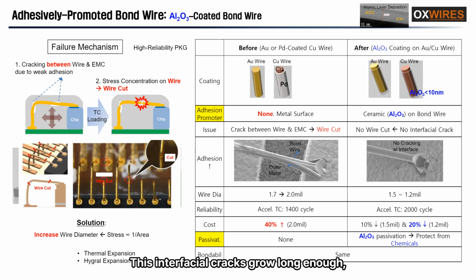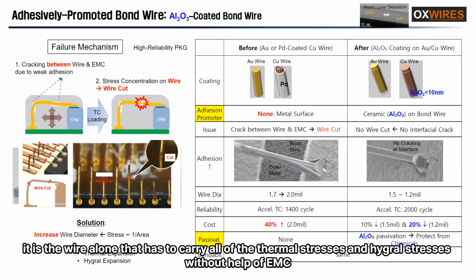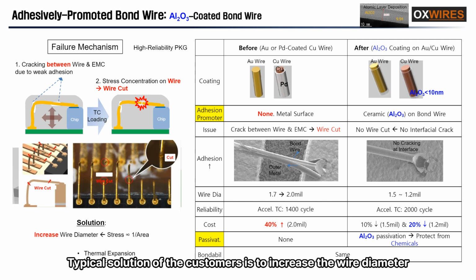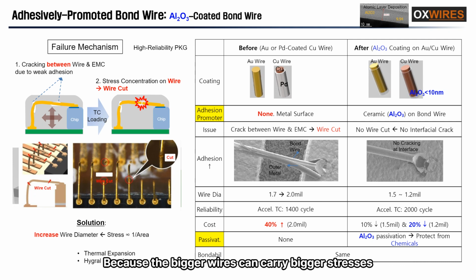These interfacial cracks grow long enough, and then wire cut occurs because, at the end of the day, it is the wire alone that has to carry all of the thermal stresses and hygroscopic stresses without help of EMC. The typical solution of the customers is to increase the wire diameter, because bigger wires can carry bigger stresses.